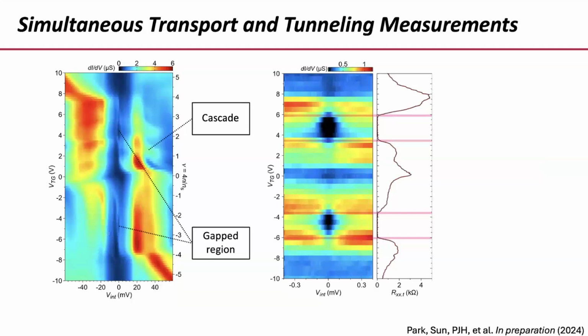And this is the differential tunneling conductance. You can see these dark regions, regions of very low differential tunneling conductance. And I can simultaneously, or right before or right after, measure the intralayer resistance through the top magic angle trilayer graphene. And that shows me this. I have the resistivity as a function of top gate voltage. And I have these regions of superconductivity, zero resistance.